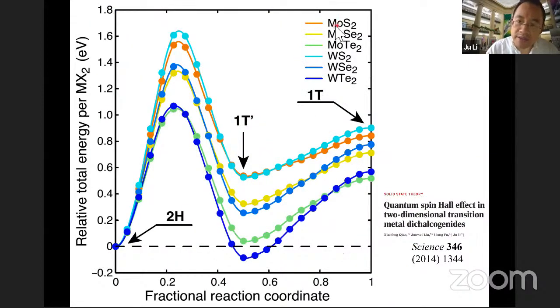And so when you look at molybdenum and tungsten, sulfide, selenide, and telluride, then we found that all their T structures are unstable. They're going to reconstruct into this 1T prime structure, but only the tungsten ditelluride has a lower energy than the H structure. As also the moly ditelluride is kind of similar. The other ones are thermodynamically only metastable compared to the H structure.